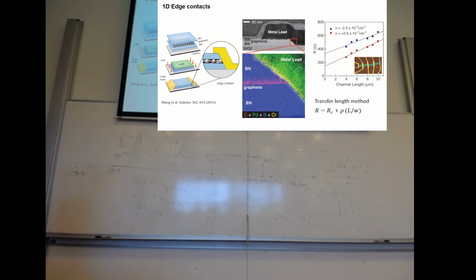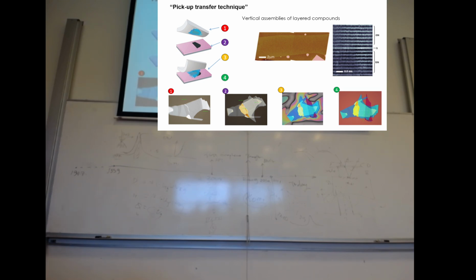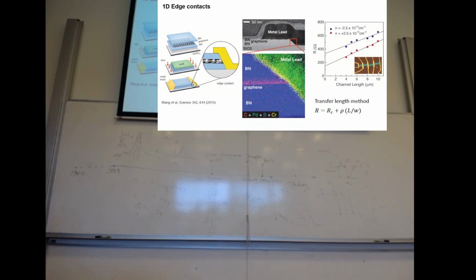So the previous discussion was on how to get rid of scattering impurities in graphene. People found two ways: one is to suspend graphene, the other is to find a substrate. One substrate apparently is not enough. So Corey later on, in 2013, developed a beta version of this technique using dry transfer instead of the wet transfer before. You can use the stamp, like I described in this slide, to do the stamping again and again, and you have a sandwich-like material vertically assembled.